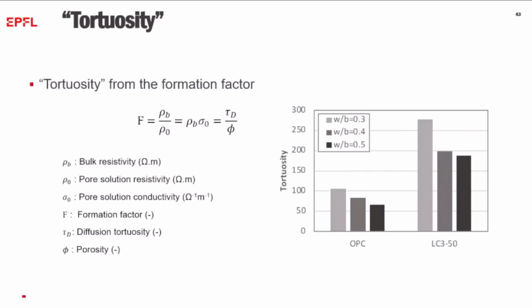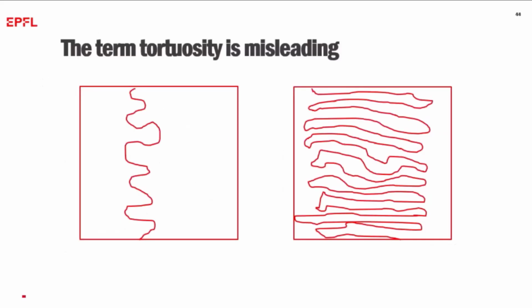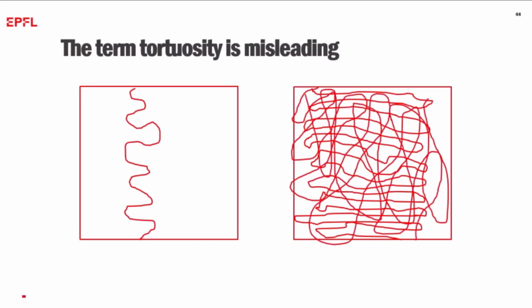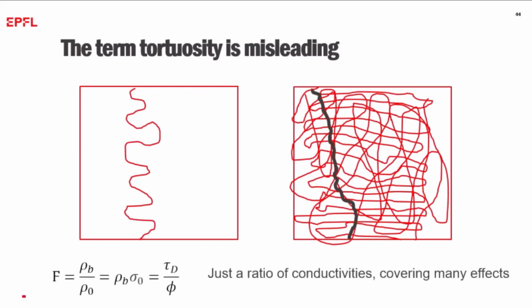And then we calculated this thing people call tortuosity. And I'm going to tell you, well, we have this idea tortuosity is pore complexity, but it's really not the whole answer. And we see these very nice high tortuosities, but as I want to stress, the term tortuosity is misleading. We think of it as being, well, the ion has to go through this complex pore path, and to get these very high tortuosities in the range of 100, you'd have to have an incredibly tortuous pore path, but you really can't produce that in a statistically isotropic material because you have another tortuous path like that, and you can always find a shortcut through here. So the problem is that the way we define that, it's really just a ratio of conductivities, which is covering many different effects. And we've looked at this in more detail.